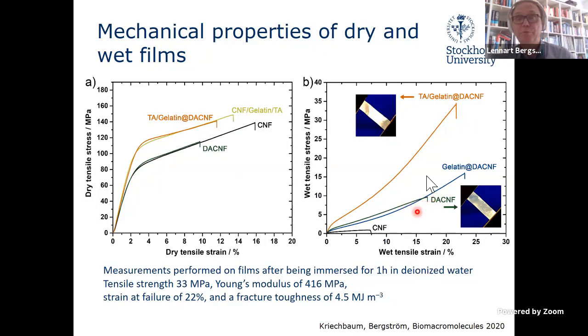The material improves with surface modification and grafting, but the real improvement comes with the precipitation of the gelatin, where we can reach a wet tensile strength of about 35 megapascals and a strain of failure of about 20%, which is quite a promising property.